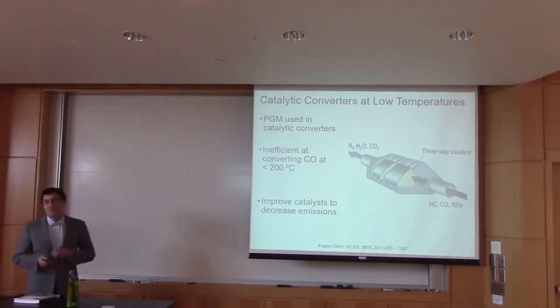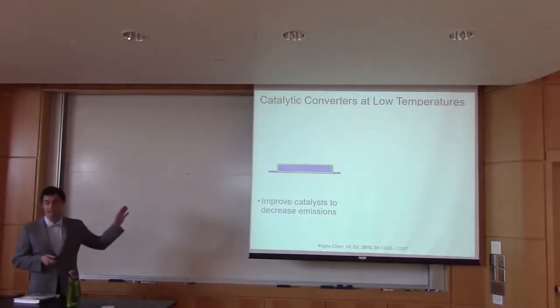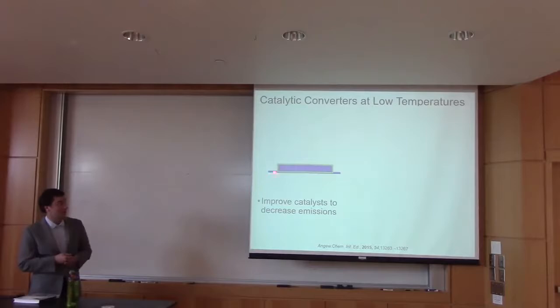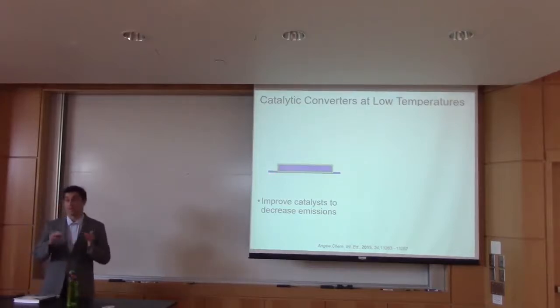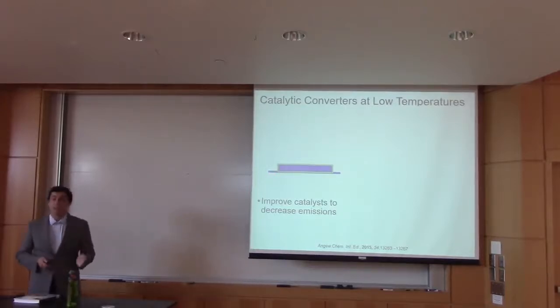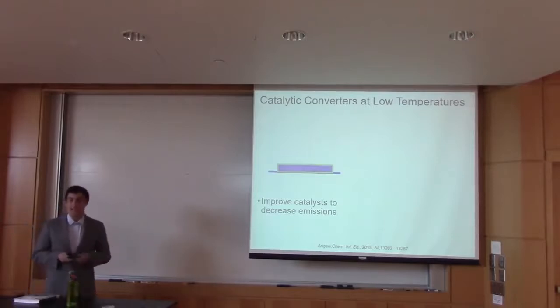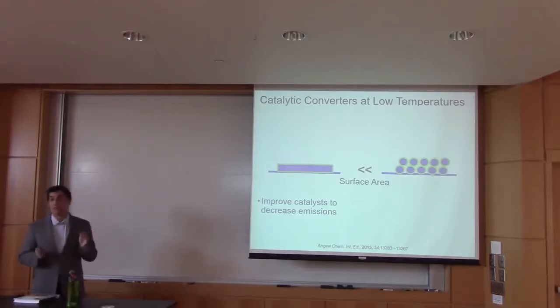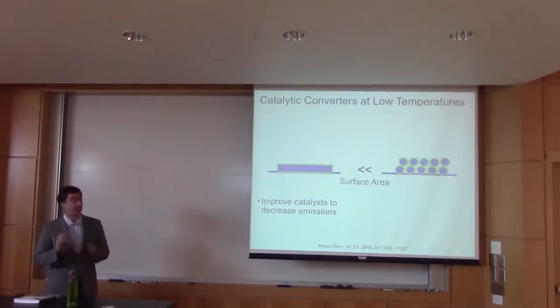Now, how we're going to do this is through a MOF templating process, which I'm going to get more into in a second, but you can think of it as this is a traditional catalyst, very simplified picture. Our chemistry is happening at the interface, this green box around it. If we can increase that surface area and break up this catalyst, we can have more active sites and more places for that chemistry to occur and have a more efficient catalyst. So we're not going to be using platinum group metals, but we're going to target this weakness using a different catalytic system and use this MOF templating technique to create this more efficient catalyst.